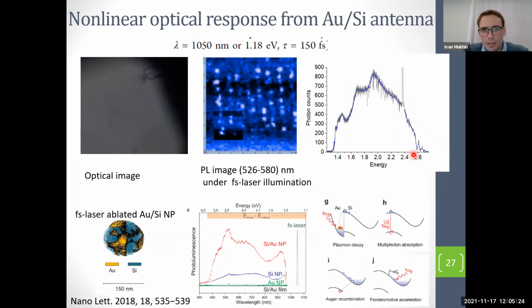This is the experimental spectrum. You can see that we have an extremely broad PL signal associated with transition of hot electrons and holes from gold to silicon and their recombination. And this spectrum shows that we have a very, very broad enhanced local density of optical states, which is very important. It's very good for efficient solar cells and efficient optical sources. So this is the conclusion of my talk.